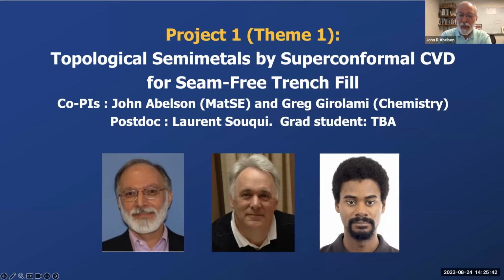Very briefly, I've been working in thin film science for over 40 years, the last 20 or 25 in a close collaboration with Greg. Greg is a maker of new precursors for chemical vapor deposition. I work in the kinetics and understanding of the thin film growth and, of course, characterization. So this is the team which in CVD has delivered processes for conformal coating, which in many cases are really competitive with ALD, and then some breakthrough work developing superconformal coating, and that's what we use to get seam-free complete fill of features like trenches and vias. We can go to the next slide.